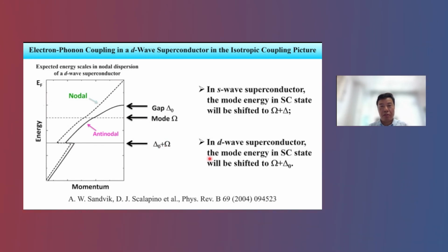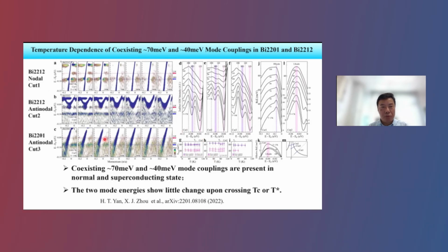In our case, we can measure both Bi2212 and Bi2201, and we don't see any energy shifts across Tc. So this is quite unusual. In the literature there are some discussions, but so far we don't have any theory to explain why the mode energy doesn't change with temperature across Tc.